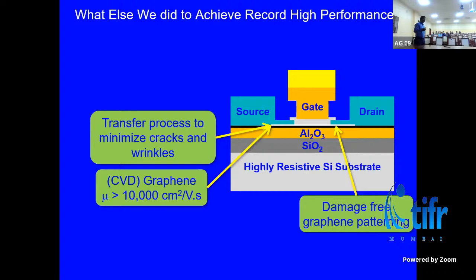And again, gate stack. How do you make these insulators for the gate to work? I mean, you cannot grow oxide. Graphene has no native oxide, right? It's not like silicon oxide. If you oxidize graphene, it becomes carbon dioxide. If you try to deposit anything, like with TMDs, it's an ultra smooth surface. We want it ultra smooth, that's what these processes were about. But now on that ultra smooth surface, depositing dielectric by ALD becomes highly challenging, right?